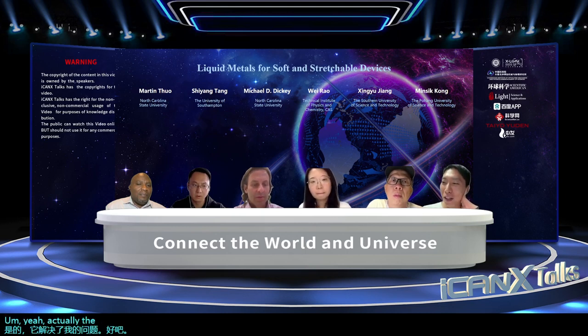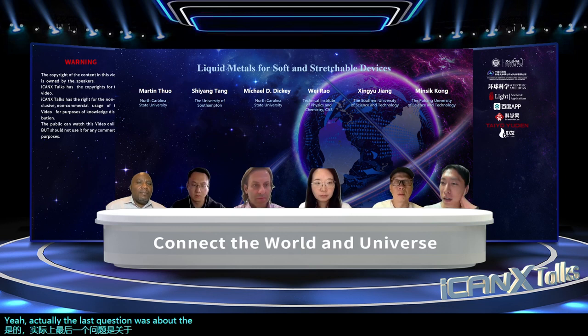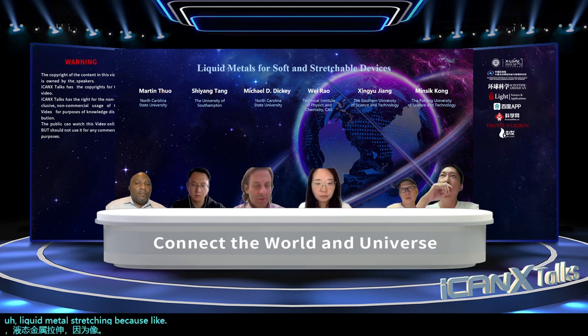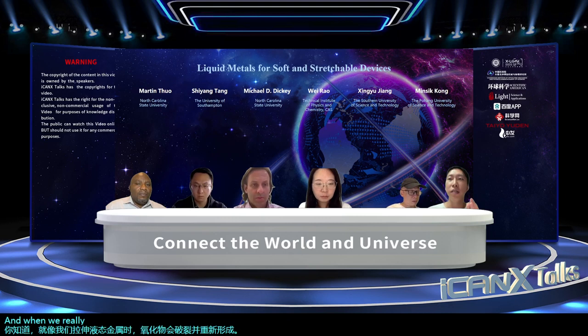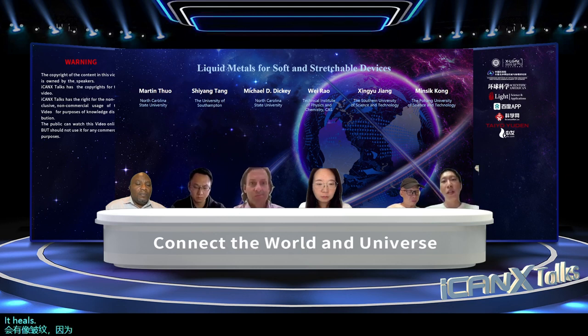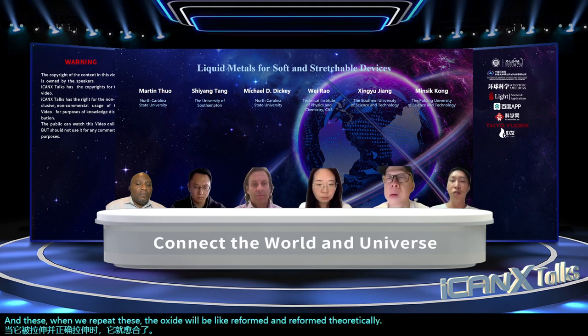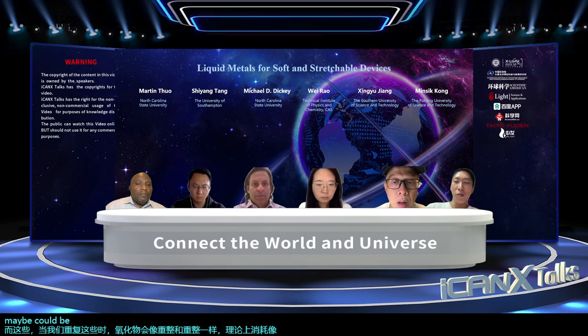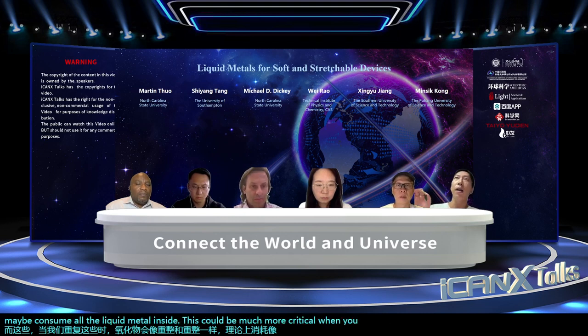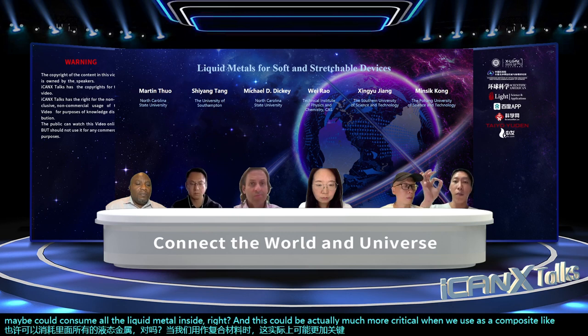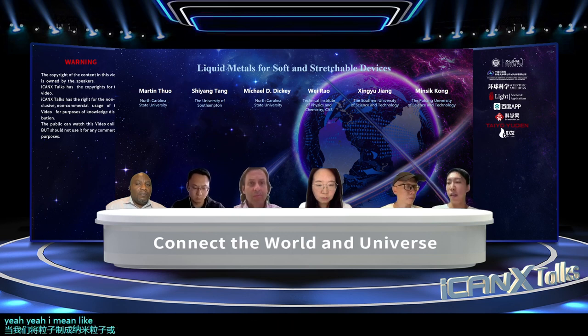Actually, the last question was about the liquid metal stretching. When we stretch the liquid metal, the oxide will break and reform, and when we release the stress, the oxide will have wrinkles because it healed when it was in the stretched state, right? And when we repeat this, the oxide will be reformed and reformed, theoretically consuming maybe all the liquid metal inside, right? This could be much more critical when we use it as a composite, like when we make the particles as nanoparticles. In those kinds of applications, it will be quite critical.